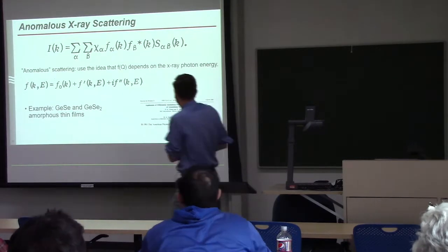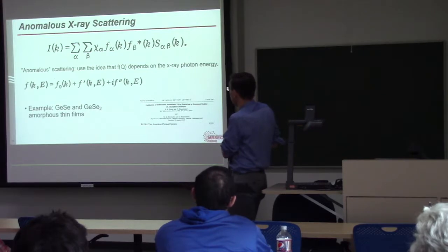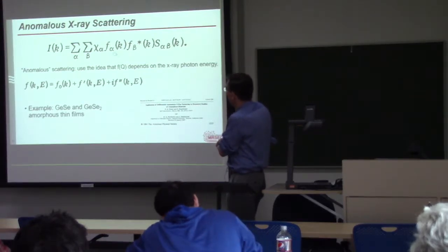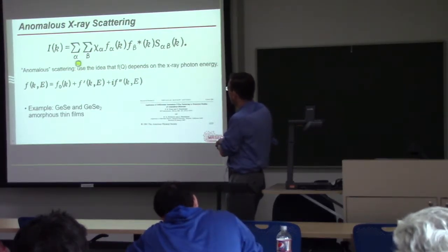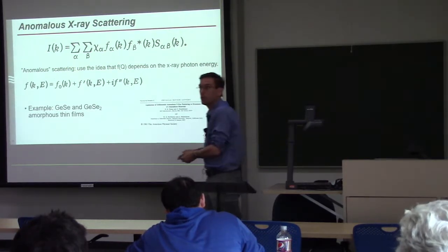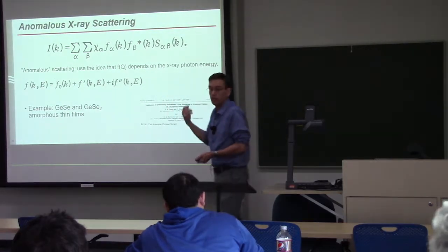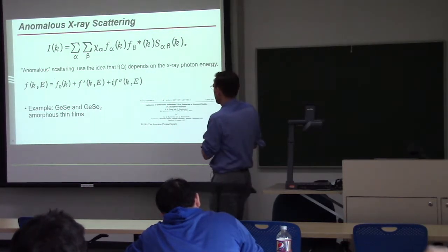It turns out to be a relatively straightforward trick. It was first applied to these types of materials in the early 80s. And you can do that, and you can extract the S alpha beta parameters, and you can learn about the coordination of individual ions within the amorphous solid. And there are some examples.